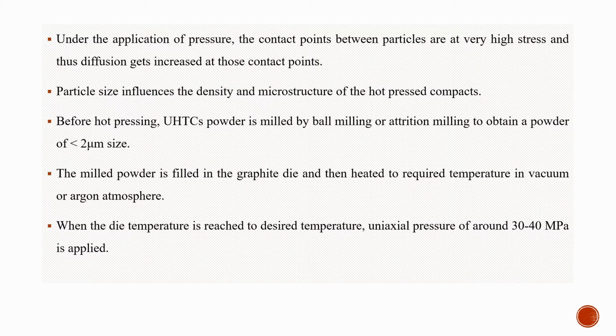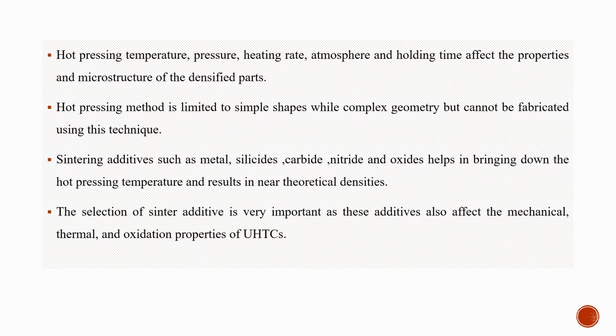Before hot pressing, UHTC powder is milled by ball milling or attrition milling to obtain a powder of less than 2 micrometer size. The milled powder is filled in the graphite die and then heated to required temperature in vacuum or argon atmosphere. When the die reaches the desired temperature, uniaxial pressure of around 30 to 40 MPa is applied. Hot pressing temperature, pressure, heating rate, atmosphere, and holding time affect the properties and microstructure of the densified parts. The hot pressing method is limited to simple shapes, while complex geometry cannot be fabricated using this technique.